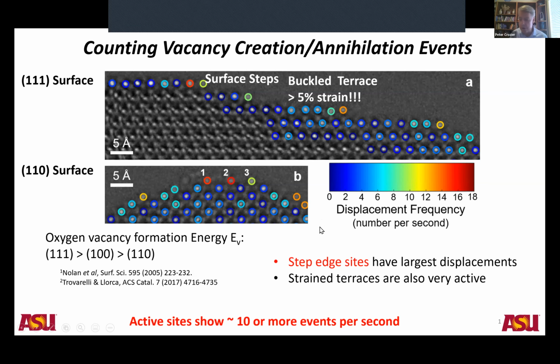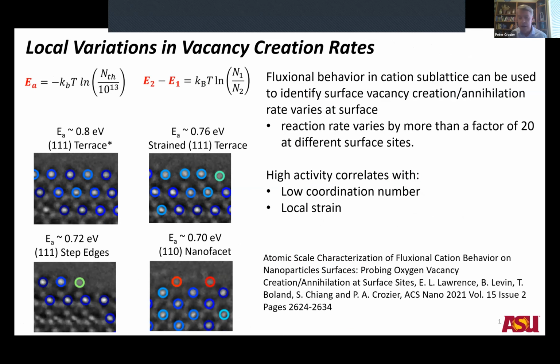And you can take that further. You can actually go ahead and calculate activation energies. If you just assume simple Arrhenius relationships here, you can determine the activation energy for oxygen vacancy creation and annihilation at different sites on the surface. And typically in these experiments, we see changes on the order of 0.10 electron volts, which, remember, even though that might sound like a small number, that translates into factors of 20 or more differences in the activity of those sites for oxygen exchange at the surface.